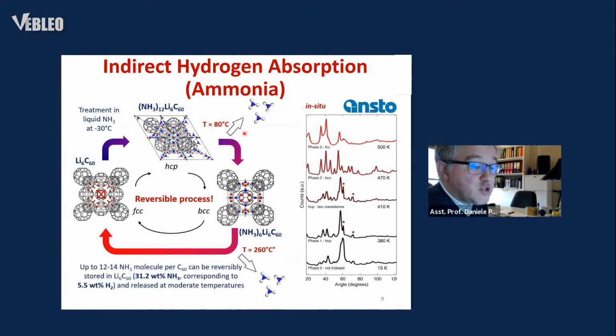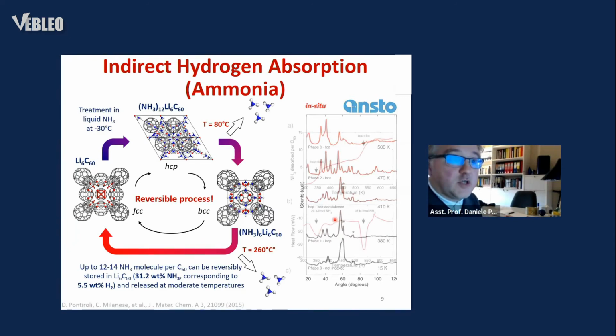We found that the interaction of lithium cluster intercalated fullerides with liquid ammonia brings to the formation of novel metastable ammonia co-intercalated lithium fullerides, which are stable near room temperature. By heating the sample, we managed to follow two phase transitions starting from the perammoniated precursor, respectively at 80 and 260 centigrade degrees, which we studied by means of in situ high flux neutron powder diffraction and differential scanning calorimetry.